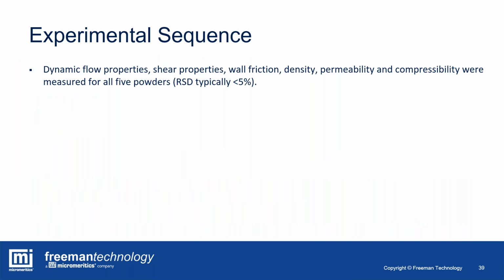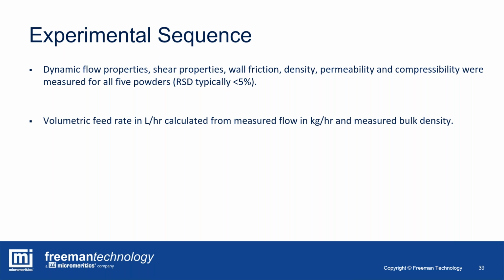And so they ran dynamic flow property tests, they ran shear tests, wall friction, density, permeability, and compressibility on all 5 materials, typically resulting in RSDs of less than 5%. The volumetric feed rate in litres per hour was measured, or calculated, I should say, from the measured mass flow rate in kilograms per hour and a knowledge of the measured bulk density. So they simply used a balance to record how much mass was being accumulated per hour effectively, and from that we could back out the volumetric displacement over that duration based on the knowledge of the density.